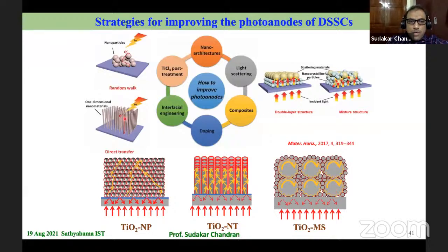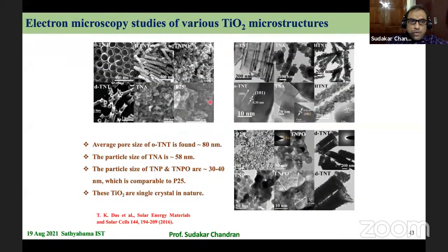So in order to effectively remove the electrons, you need to have a good connection between the nanoparticles, or people have explored one-dimensional structures. But then the light is also not getting scattered or effectively used. So people use different kinds of scattering layers. Lots of approaches are used. But what we found in our very preliminary studies earlier is that the oxygen vacancies, which are present to a different extent in various nanostructures, affect the solar cell efficiency.